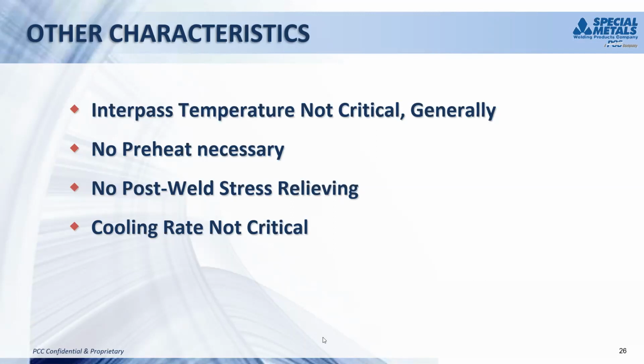Now, there are some applications where you might get into stress relaxation cracking, and you will need a post-weld stress relief for those. But typically, you don't really need post-weld stress relieving. And finally, the cooling rate is not critical. So we keep a bucket of water if we're welding on something that is not critical. We just dunk it in the water to keep it cool so we can keep welding.